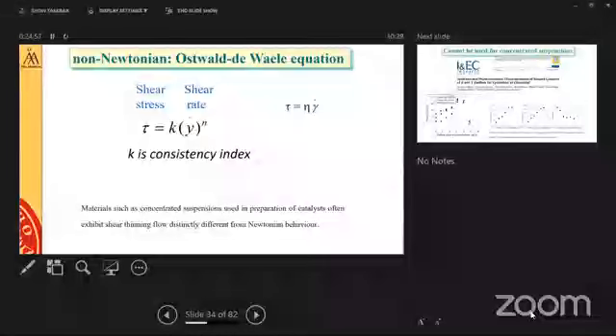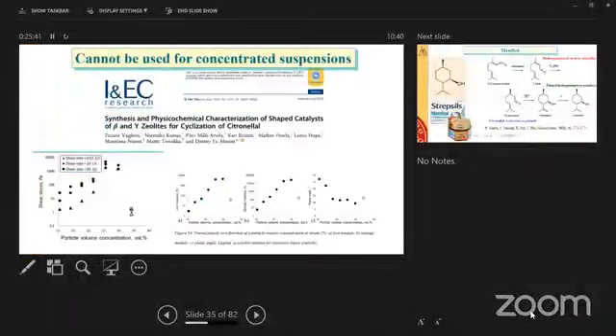So at some point, I was thinking that we can bring more science to this art of shaping by studying rheology. Rheological properties, how the paste goes through the extruder. And then I was using relatively well-known and established equations for non-Newtonian movement of liquids, or fluids. But the problem is the concentrated suspensions, they have much higher concentration of the solid than even we are able to measure for different type of rheological measurement.